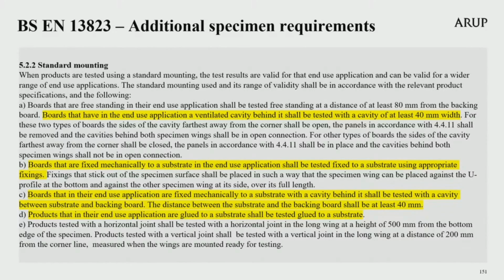When products are tested and mounted as in their end-use applications, the test results are then valid only for that application. When products are tested using a standard mounting, additional guidance is provided. For example, boards in the end-use application of a ventilated cavity behind it shall be tested with a cavity of at least 40 millimetres. Boards to be mechanically fixed to a substrate in their end use should be test fixed to a substrate using appropriate fixings. And products that in their end use application are glued to a substrate shall be tested glued to a substrate.